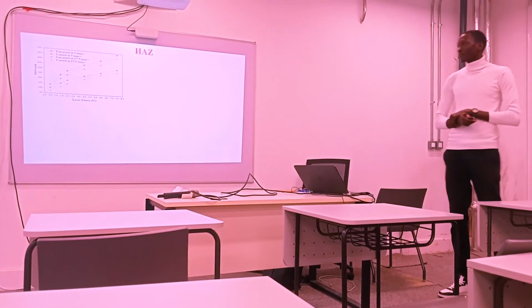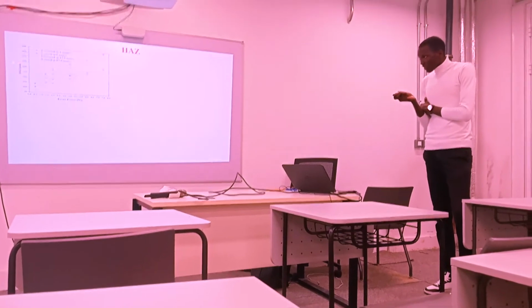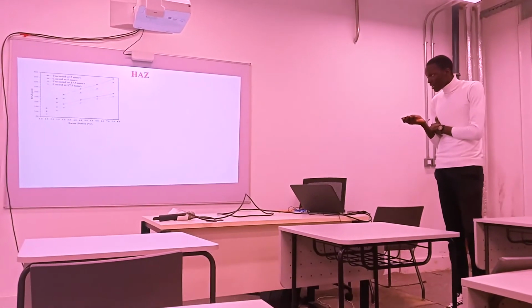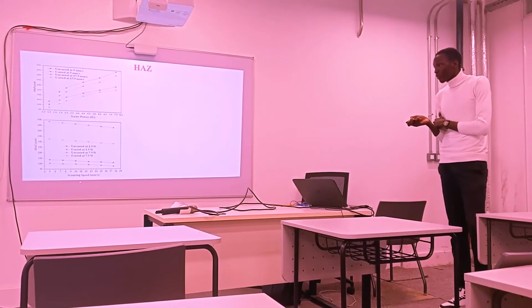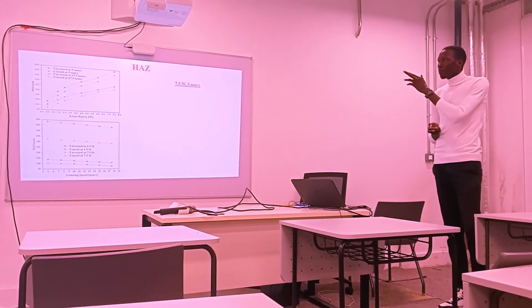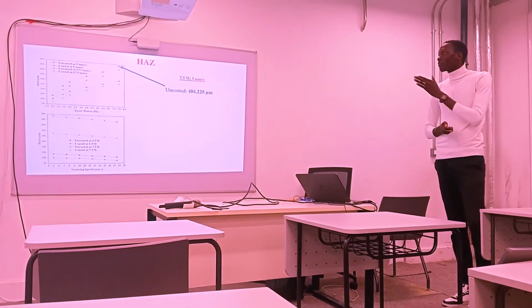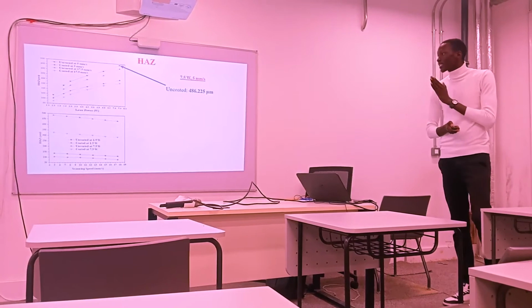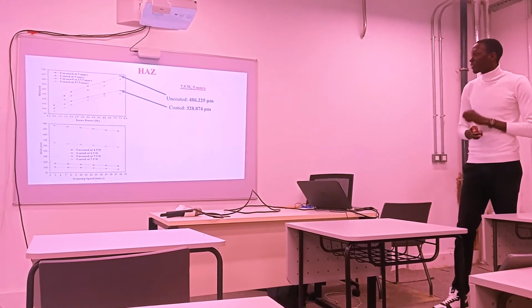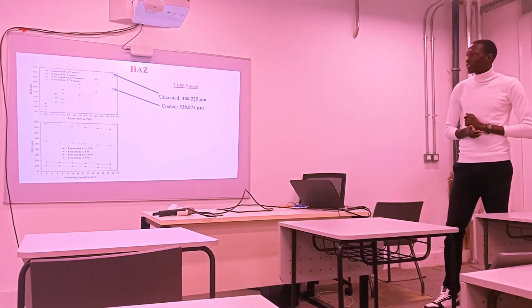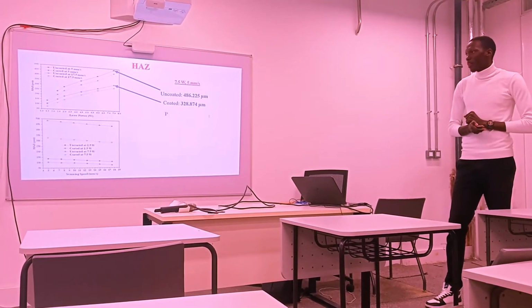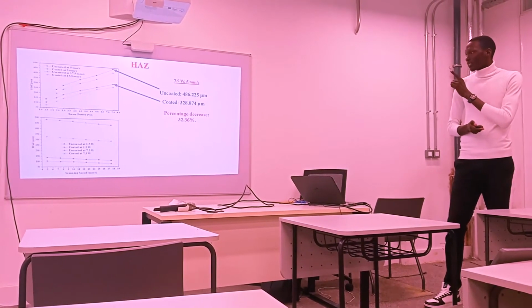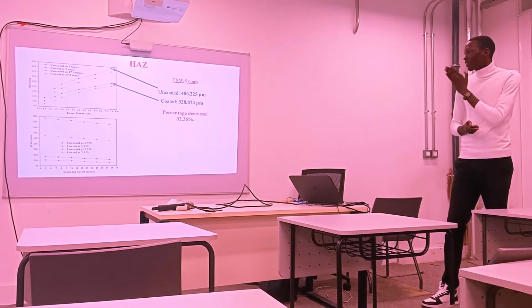Then heat affected zone, the final parameter. We plotted heat affected zone with laser power and heat affected zone with scanning speed. At maximum power and minimum speed, we got the value for the uncoated to be 486.225 micrometers. This value reduced to 328.874 micrometers for the coated sample. Now, the percentage decrease is 32.36%.